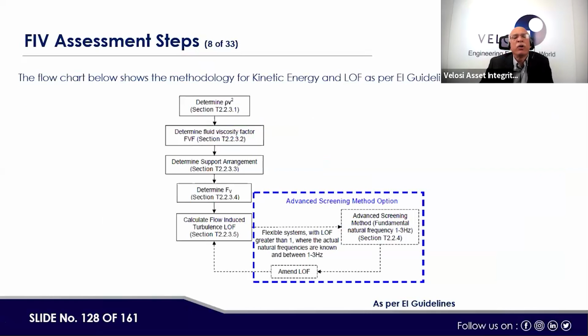Then, like how we calculate the kinetic energy calculations, which is PV square, determine the fluid viscosity factor first, then determine the support arrangement as per the sections, then determine FV as per the section, the calculation of flow induced turbulence LOF, section T2.2.3.5. Then the advanced screening method can be used, like the advanced screening method for fundamental natural frequency, which is 1 to 3 Hertz, section T2.2.4. Then for a flexible system with LOF greater than 1, where the actual natural frequency is known and between 1 to 3 Hertz, amend the LOF basically.